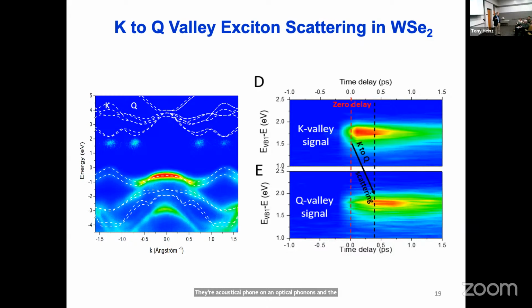So you actually know that you're dominated by optical phonon scattering. And if you look then at the dynamics here, it can tell you about the electron-phonon coupling strength. So the interesting thing is we did a study previously of the variation of the line width with temperature for exactly this exciton. And we saw the onset of a broadening that you could correlate with an activation energy of a phonon, but it was all a pretty indirect story about what was going on. We could really only understand the results if we assumed there was another valley and you opened up another scattering channel. So this was like a missing piece of the puzzle that then allows us to have confidence that what we're seeing in that broadening is the influence of a phonon that connects the K and Q valleys.